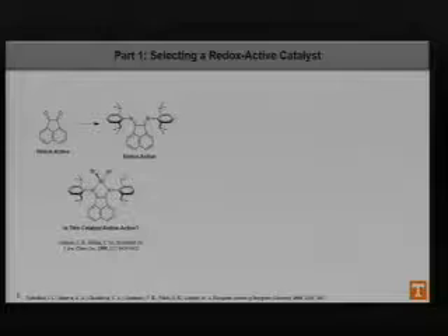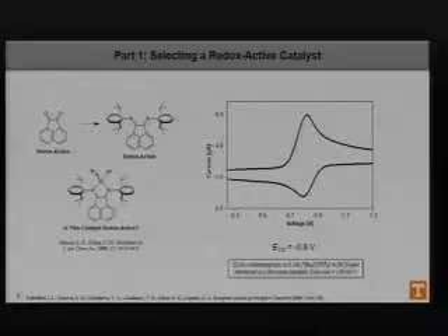So for part one, the first step was obviously selecting which catalyst that we were going to use. This catalyst was developed in 1995, one of Brookhart's original catalysts. And we found a report from 2004 that showed that the ligand that was bound to it was actually also redox active. So we thought, well, I wonder if the catalyst itself is still redox active once it's been metallated with nickel. And so we took a CV trace of this catalyst and we obtained the curve on the right. And this peak here corresponds to a reduction potential at about negative 0.8 volts, which indicated to us that it in fact was redox active.